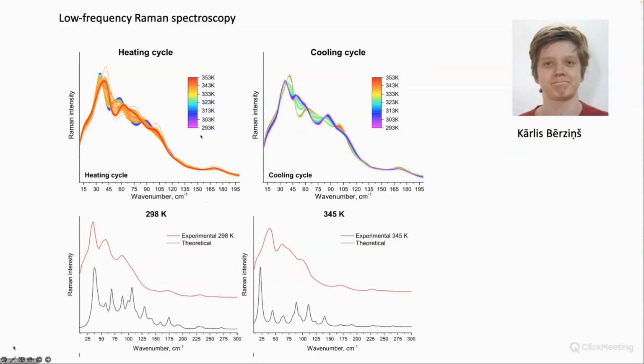And what we observe in both cases is a fairly large change in the low-frequency Raman spectrum, again indicating that the lattice dynamics is changing quite a lot between these two crystalline forms. And that, again, we can see also from the theoretical DFT calculations here that the two forms are quite different. I don't know if the agreement with the experiment is perfect, but that's something we are working on at the moment to see if we can make even better calculations.